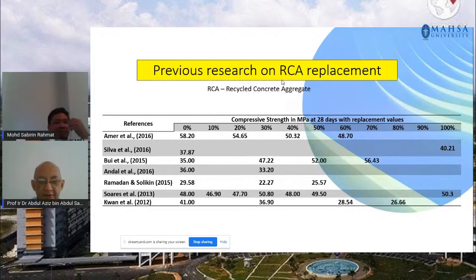Now, in terms of the RCA, the recycled concrete aggregates, I will explain what I mean by recycled concrete aggregates. In this research, again, I compiled various past research work conducted on replacing coarse aggregates with recycled concrete aggregate. Again, as you can see there, researchers have tried to replace coarse aggregate from 10% up to even 100%. But from our observation and compilation, we can see that we seem to get a reasonably good concrete strength when we only replace about 30% of recycled concrete aggregate.